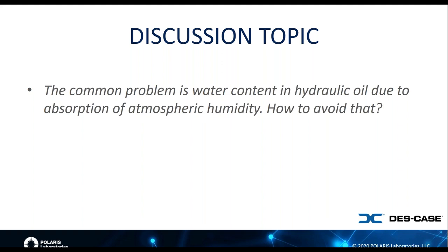But even if the oils become contaminated with water from a different source, having a desiccant breather on a tank or a system would be a benefit, again, because of Henry's law. Because the silica gel is in contact with the headspace, it will adsorb that moisture out of the headspace, which in turn will induce the oil to liberate some of the water. And you can actually bring the relative humidity in a hydraulic fluid down below 20 or 30% RH just by having a desiccant breather either on the tank or on the reservoir.